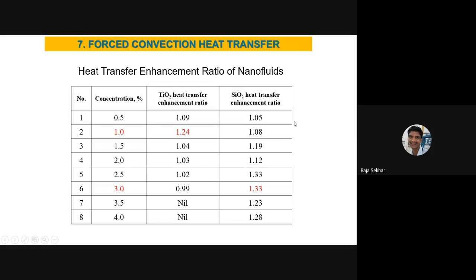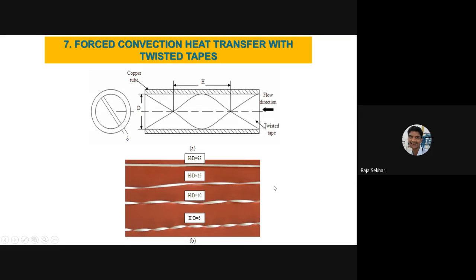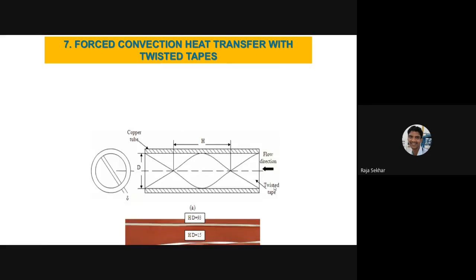Generally for laminar conditions, you can use it in electronic cooling equipment. Coming to this enhancement ratio, you can see that up to concentration 1 the enhancement ratio is 1.24. More than 1, you can see that the enhancement ratios are getting reduced. Similarly for SiO2, up to 3 it is okay. More than 3, SiO2 is not preferred because the enhancement ratio is falling down. And you can use these twisted tapes along with nanofluids for enhanced heat transfer.